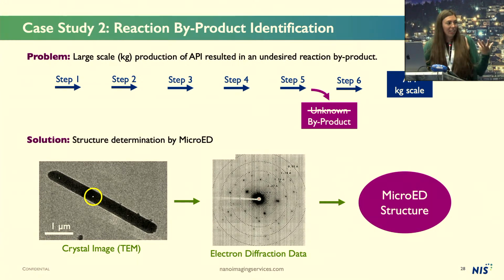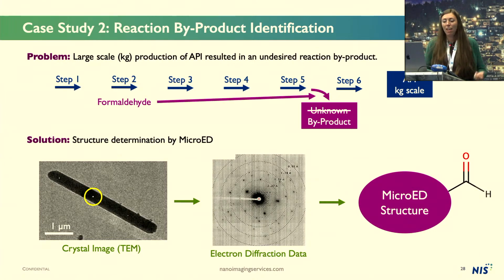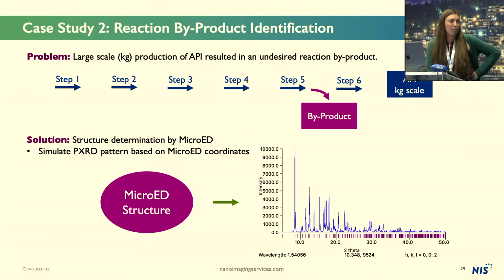So one other thing in looking at the structure that we were able to see is that there was an addition of a formyl group to the compound and some unusual ring rearrangements that had occurred. And so from this, they were able to realize why this product was occurring. There was some formaldehyde from step 2 that must have been hanging around in their reaction and was reacting with the product from step 5 and producing this unwanted byproduct. So then they could go back and design a better strategy for production that removed this formaldehyde and prevented this from happening.